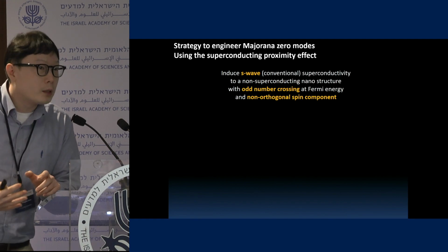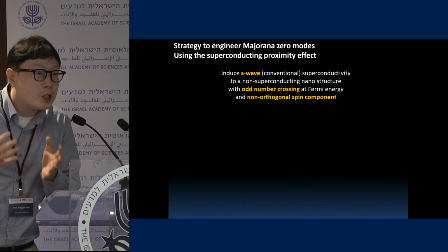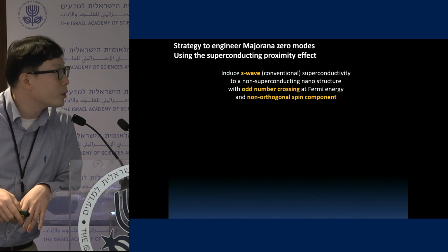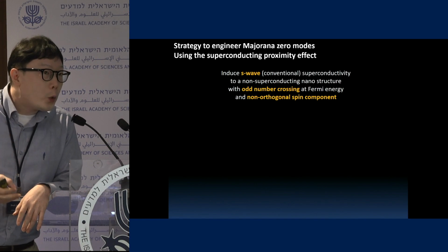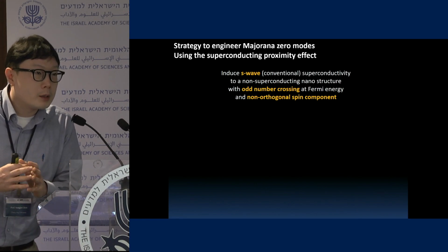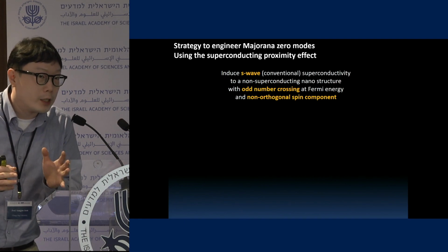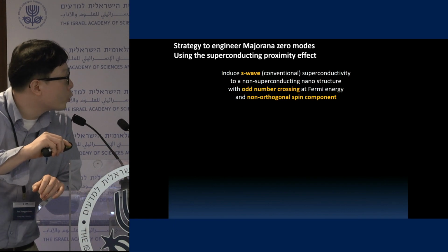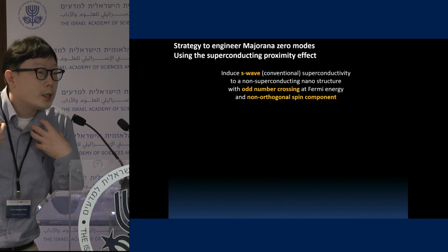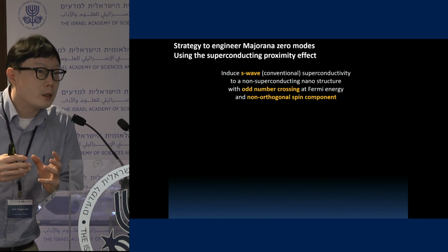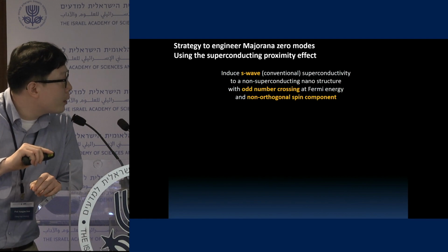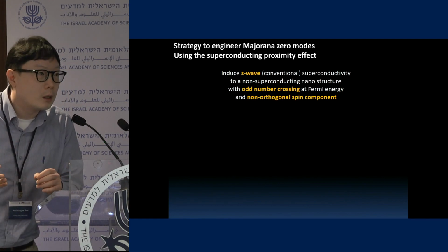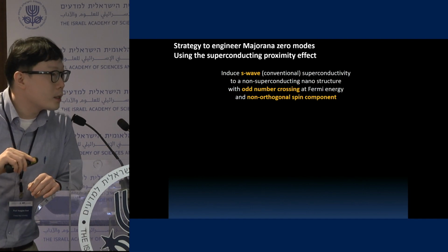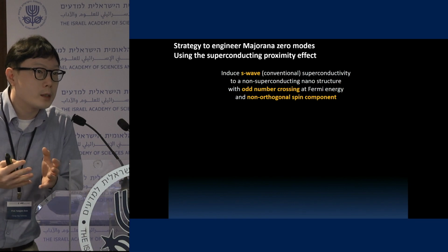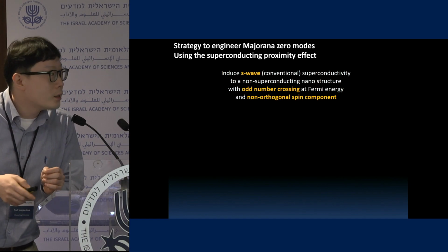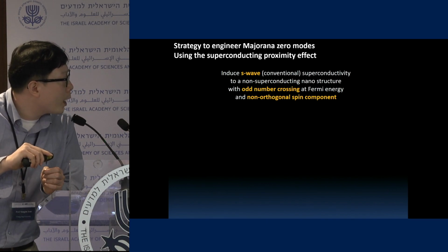And then, as an experimentalist, how we engineer and realize this Majorana zero mode is as follows. Starting with a p-wave superconductor would be the easiest way, but as we know, p-wave superconductors are very rare in nature. So the starting point is a normal, conventional superconductor, and we try to induce superconductivity in non-trivial nanosystems. For example, this system could be a one-dimensional or two-dimensional system. And then the number of crossings at the Fermi level has to be odd. Otherwise, it will again be the trivial phase. So to get the non-trivial phase, we have this condition.